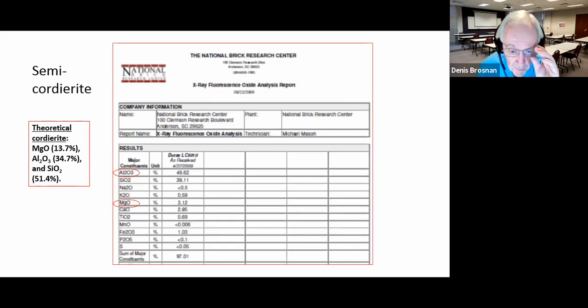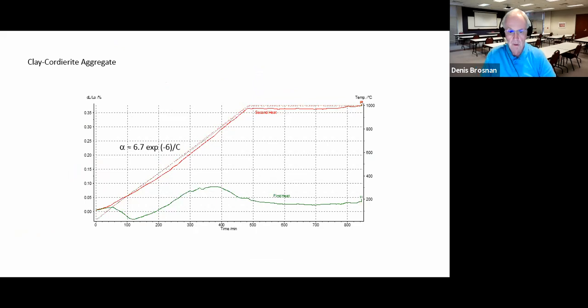So in this particular case, instead of 13.7% MgO, they only had about 3% MgO overall in the product that was made. They had about 34.7% alumina in theoretical cordierite, and you can see they got above 40 here in alumina. So they mixed clay, fire clay, and cordierite aggregate, cordierite powder from waste sources, in making this particular semi-cordierite in example A.